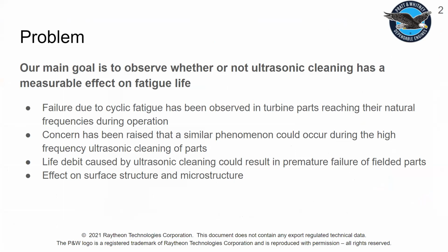So the main problem, our goal was to observe whether or not ultrasonic cleaning has a measurable effect on fatigue life. Failure due to cyclic fatigue has been observed in turbine parts that reach their natural frequency during operation. Concern from our sponsor has been raised that a similar phenomenon could occur during the high frequency ultrasonic cleaning of parts. Fatigue life debit caused by ultrasonic cleaning could result in premature failure of these parts, and it would cause an effect on the surface structure and the microstructure.